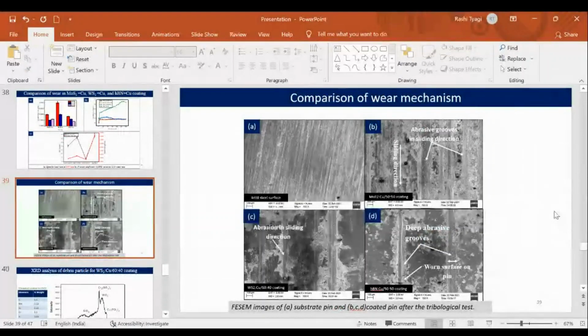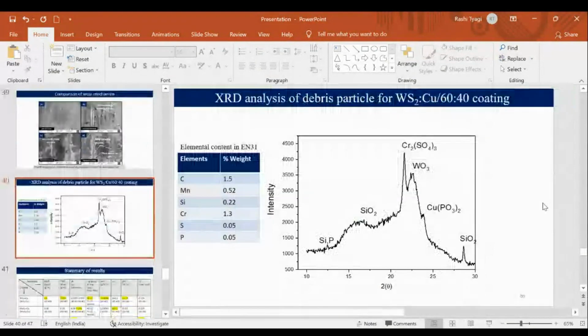So coefficient of friction is high after the coating. This is the comparison of the wear performance. You can see there is a minimum wear. These are pin images that we have captured after the coating. There are the wear tracks that we can see when the wear takes place. So minimum wear you can see for the WS2 plus copper coating. You can see minimum abrasion in the sliding direction. Deep grooves are observed for the hBN plus copper coating and the MoS2 plus copper coating.